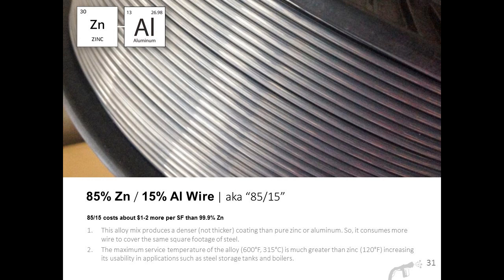So 8515, quite different, right? It costs about $1 or $2 more per square foot than pure zinc does. 8515, though, does combine the benefits of both pure zinc and pure aluminum. The alloy mix is denser, not thicker, and this is a distinction that's worth mentioning. Basically, as you use 8515 versus aluminum, it uses about 20% more wire than pure zinc to cover the same square footage of steel. So it provides a denser coating, which means you use more of it to cover the same amount of square footage. So this is really where some of the cost comes from.